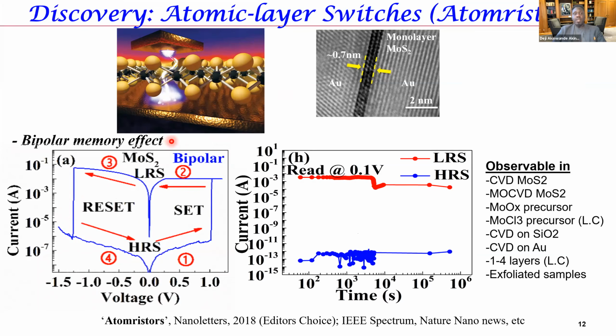So our current thinking is that even though the elemental material is the same on both sides, the geometry of the material is not the same on both sides, and I'll speak more about that when I talk about the mechanism. The geometry on the top side is a deposited gold film. The geometry on the bottom side, in this initial result, is actually a gold foil. So I think these differences in geometry may play a role, but the fact of the matter is we don't have an exact answer to that question - we just have a hypothesis to explain it. Thanks very much.